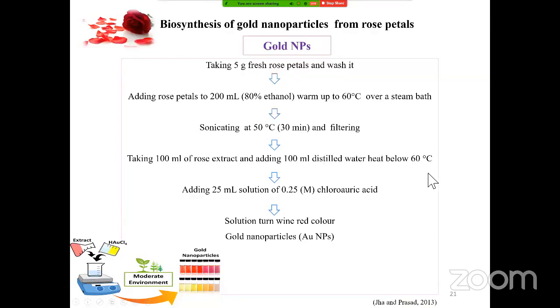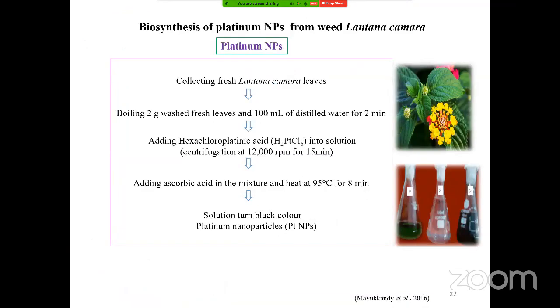The filtered rose extract, 100 ml of it, is added to 100 ml of distilled water, and again heated at 60 degrees centigrade. To that solution, 25 ml of chloroauric acid, HAuCl4, is added. Then the solution turns to wine red color, which indicates the formation of gold nanoparticles. And coming to the platinum nanoparticles, it is extracted from the weed Lantana camara.